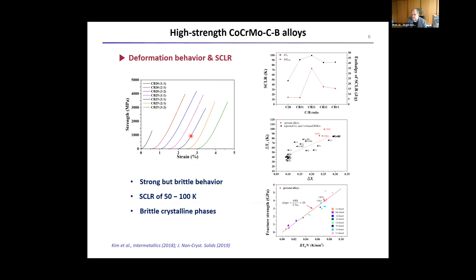The problem with these amorphous systems is typically that they may be quite strong. For such cobalt-based alloys, depending on composition, strength values of 3000, 4000, even up to 5000 or 6000 MPa are not unrealistic. So you have a very strong material at room temperature. But unfortunately, as you can see, there is basically no ductility — these materials are relatively brittle with almost no plastic deformability at room temperature.